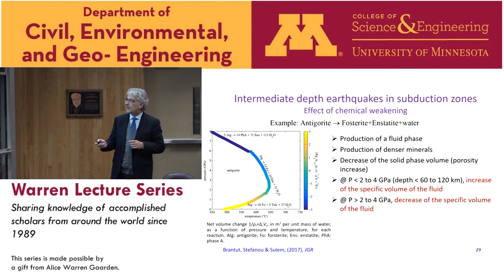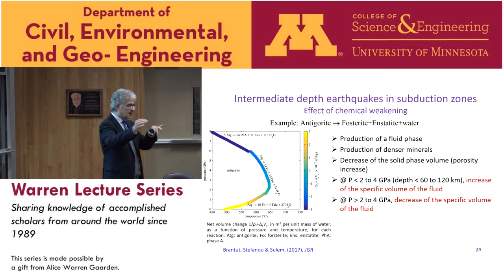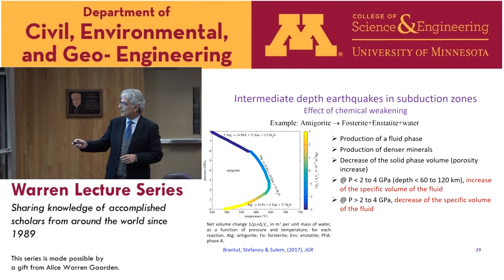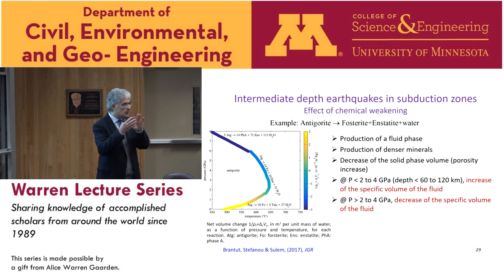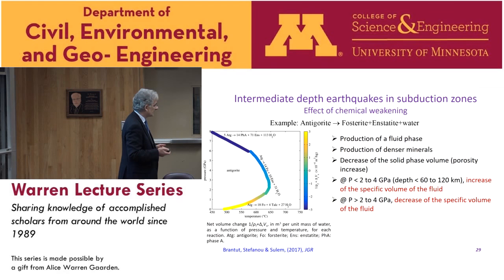two types of behavior depending on the condition of pressure. So below about 60 to 120 kilometers, so below pressures which are between 2 and 4 gigapascal, there is a net increase of the specific volume of the fluid, which means that we have a net pressurization of the fluid, because we have an increase of the porosity, but the amount of fluid which is released in the system is such that we have a net increase of the pore pressure. So increase of the pore pressure brings the state of stress back in the brittle regime because the effective stress is decreasing. So in this case, this is called dehydration embrittlement, and being back in the brittle regime, we understand that we can have instability and seismic slip.